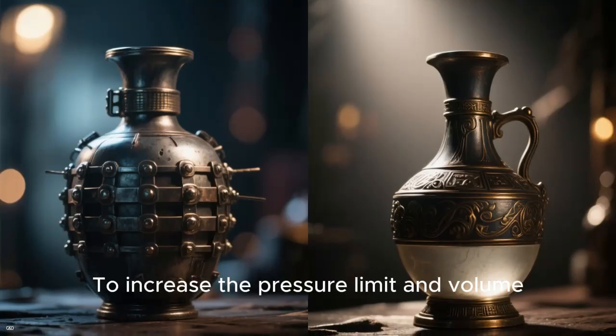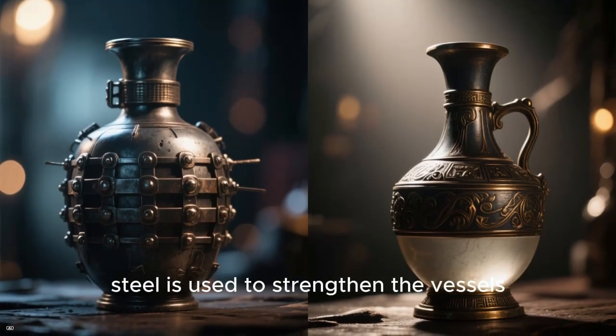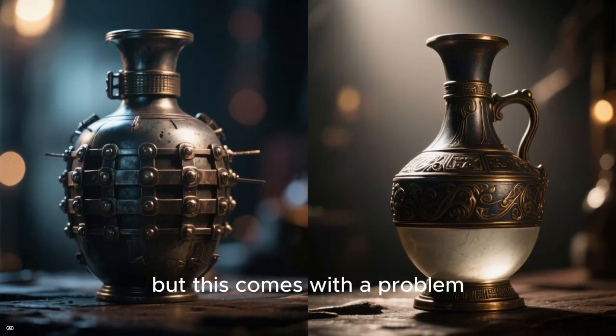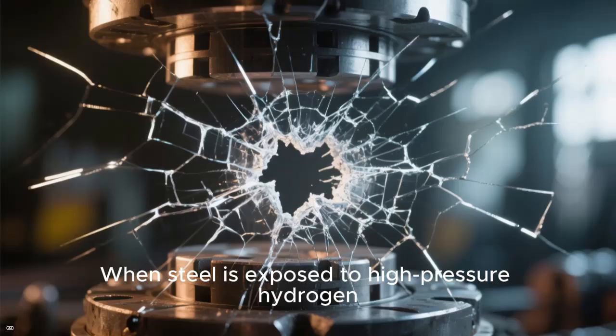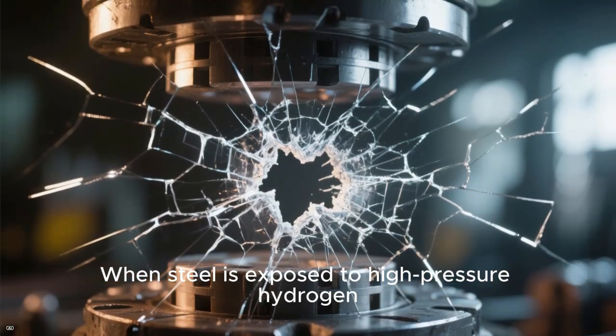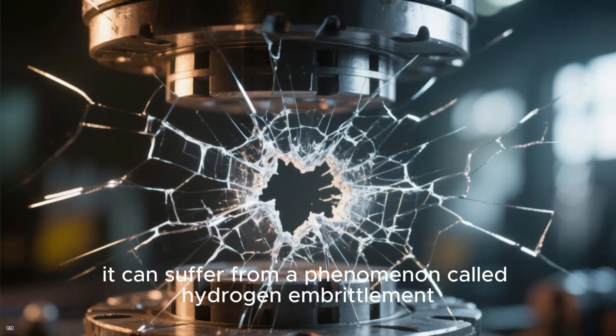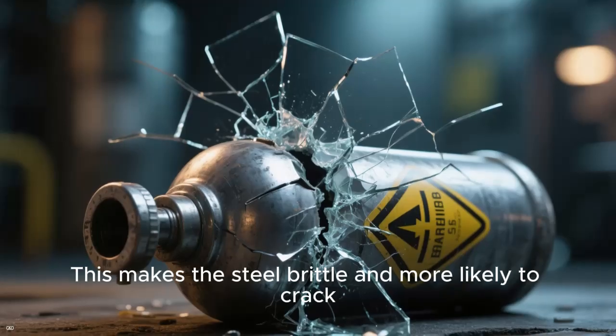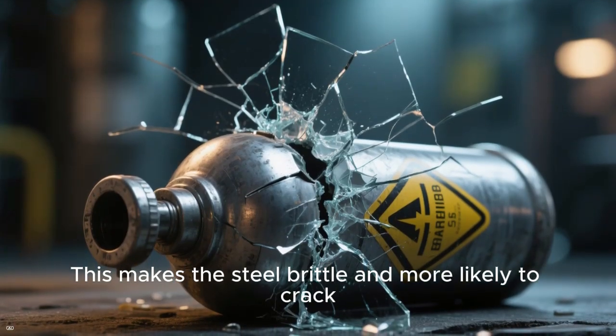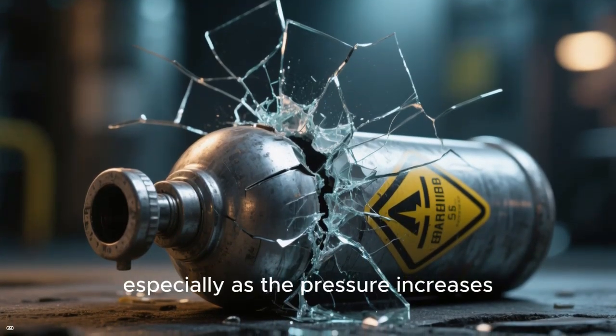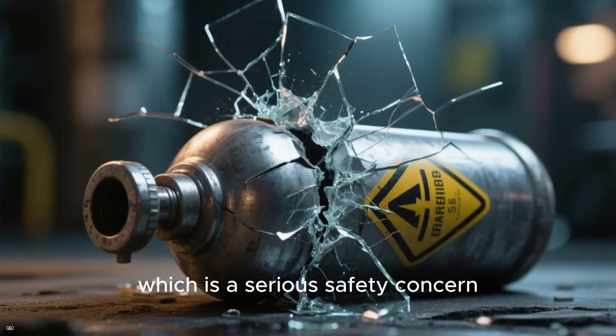To increase the pressure limit and volume, steel is used to strengthen the vessels, but this comes with a problem. When steel is exposed to high-pressure hydrogen, it can suffer from a phenomenon called hydrogen embrittlement. This makes the steel brittle and more likely to crack, especially as the pressure increases, which is a serious safety concern.